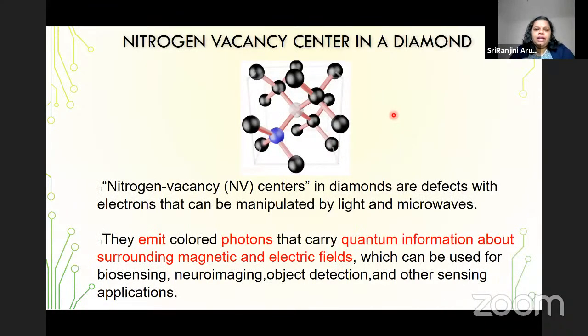So what is a nitrogen vacancy center in a diamond? What you see here is a unit cell of a nitrogen vacancy center in diamond. As I told you before, it's all made up of carbon, which is black in color. All the carbons are marked in black. You take out one of the carbons, knock it out, and replace it with nitrogen. So you get a nitrogen center in diamond. Also knock out the adjacent carbon and make it a carbon vacant site, and it is balanced by the lone pair of electrons from the nitrogen. So the valency is satisfied and it's a very stable system.